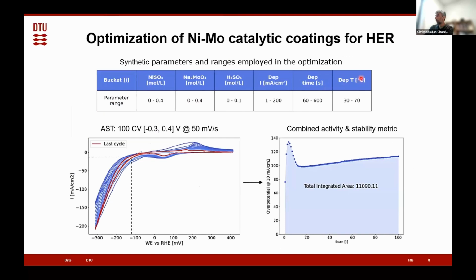This is a list of the parameters that were included in the optimization and the ranges employed. So that was the amount of nickel and the molybdenum precursors in the electrodeposition solution, the pH of the solution, the deposition current time, and deposition temperature.